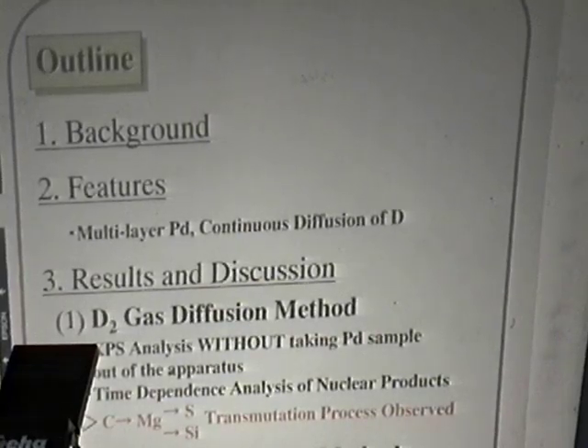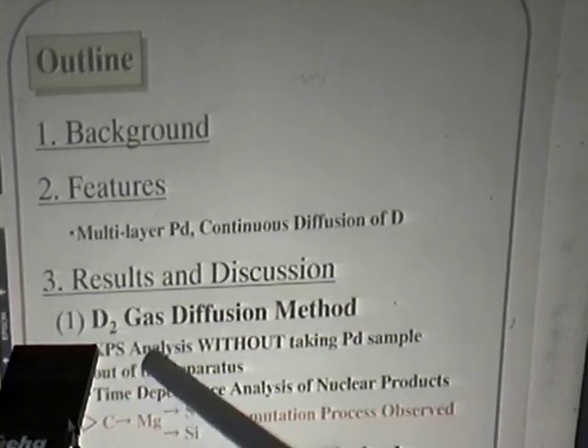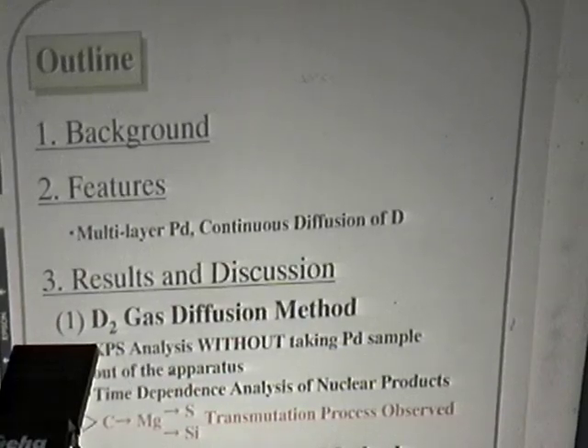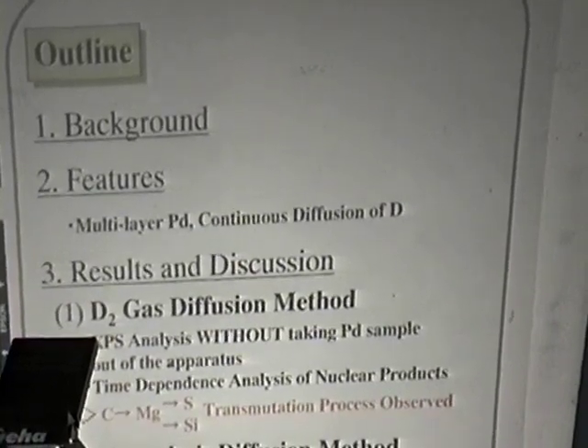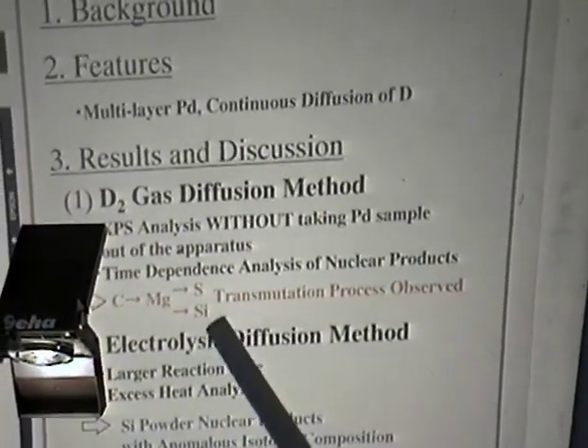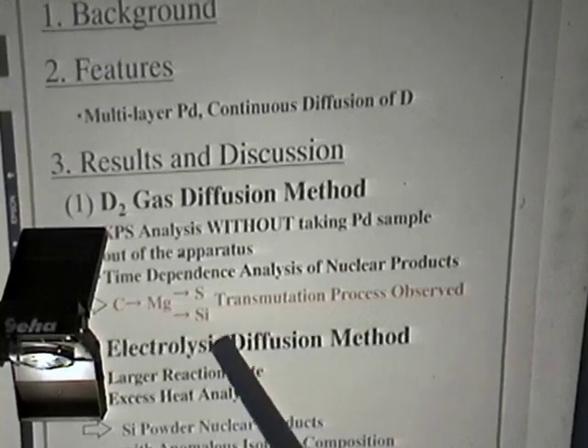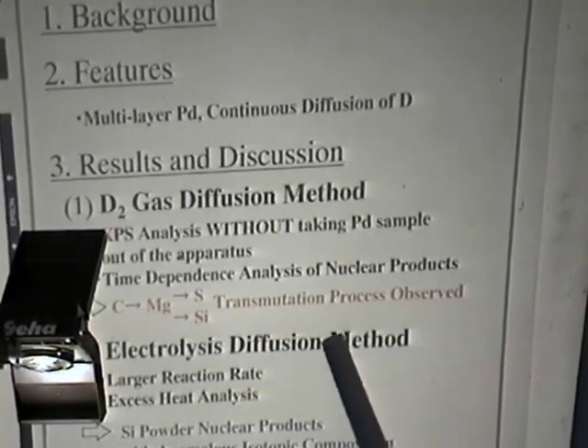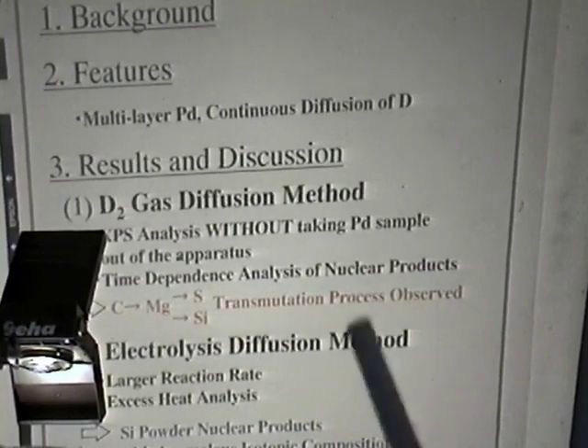The D2 gas diffusion method can analyze the elements on the palladium sample by XPS, X-ray photoelectron spectrometry, without taking the sample out of the vacuum chamber. It is also possible to analyze the time dependence of nuclear products. And from carbon to magnesium, to sulfur or silicon, the transmutation process was observed by this method.